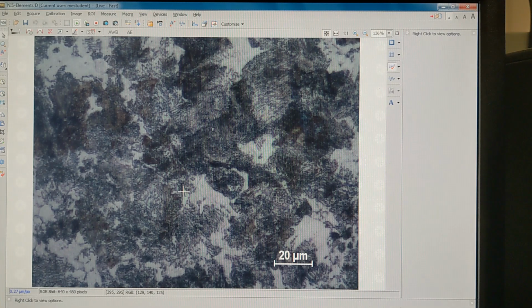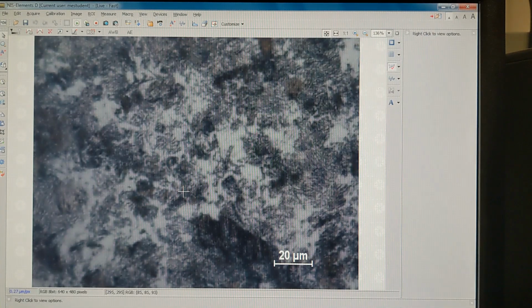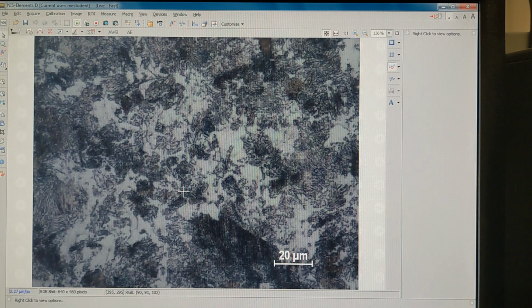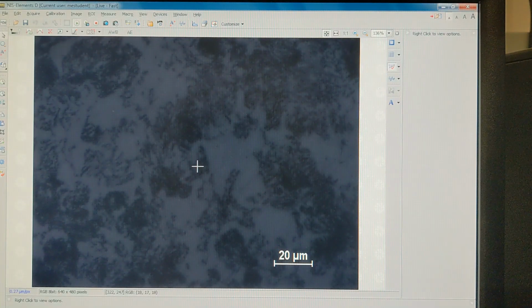If we go to a different location, about here, this region seems to have a little more ferrite, but we still have our kind of layered pearlite here and here. If we zoom in to 100 times, it's darker, but the pearlite becomes slightly more visible.